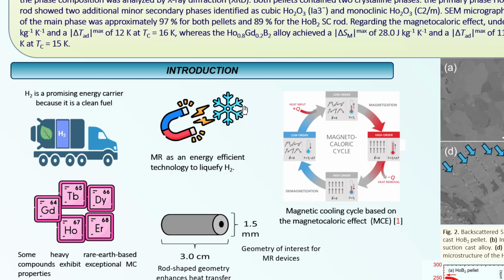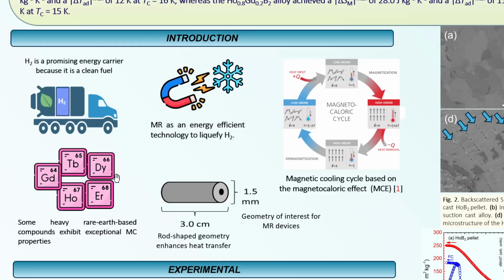The key is to design materials with strong magnetocaloric responses, close to 20 Kelvin, which is the liquefaction point of hydrogen. Among the candidate materials, rare earth intermetallic alloys stand out, and in particular, holmium diboride has been considered a benchmark material because it exhibits a large magnetic entropy variation and adiabatic temperature variation at the right temperature window. However, to implement these alloys in real devices, they must be fabricated in specific geometries, such as rods, to improve the heat transfer and integration into magnetic regenerator beds.